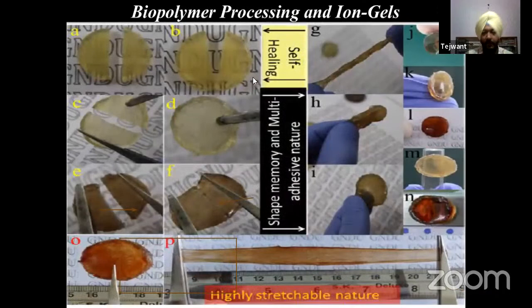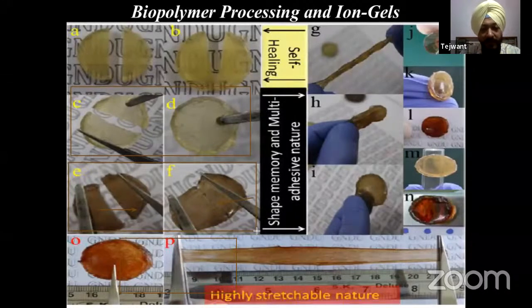In that case, the most interesting property we have found in this gel is the self-healing property. Self-healing means if you cut the gel in two pieces, you can see in panels C and D, and you combine the pieces, it self-heals within less than a minute. It has been happening with the simple ionogel. The same thing happened when the two cut pieces of ionogel having silver oxide nanoparticles were adhered with each other. On the other hand, the hydrogel, as shown in panel A, never self-heals.